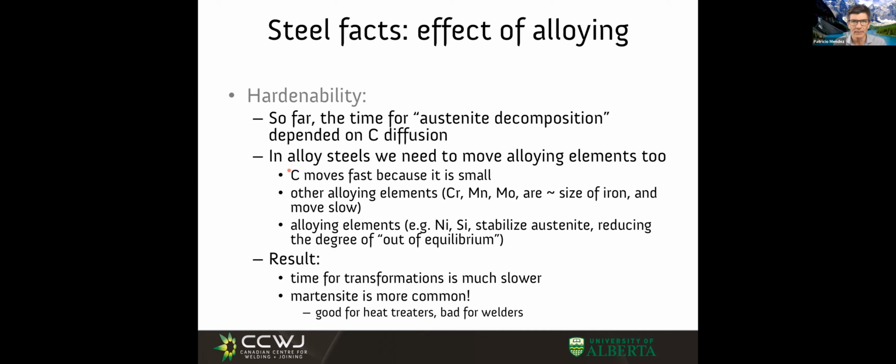For people doing heat treatment, this is awesome, because if you wanted to do, for example, a very, very big shaft that you wanted to temper, to do some sort of a quench, the inside of the shaft doesn't matter, you can quench it at 0 Kelvin on the outside, and the laws of heat transfer, which many of you took with me, say that even if the surface is at 0 Kelvin, the core takes a long time to diffuse the heat away, to take the heat away. I'm not talking about mass diffusion, I'm talking about diffusion of heat, of which we have a whole course, right?